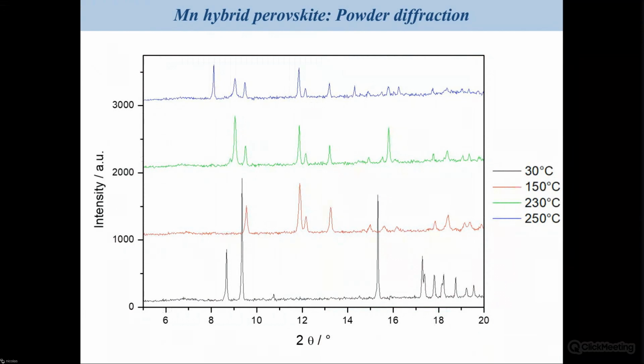So these are the spectra of the different temperature domains. And again, you see that the larger differences are observed between the 30 Celsius degree graph and the 150 Celsius degree, which is corresponding to the very big endothermic peak described previously.